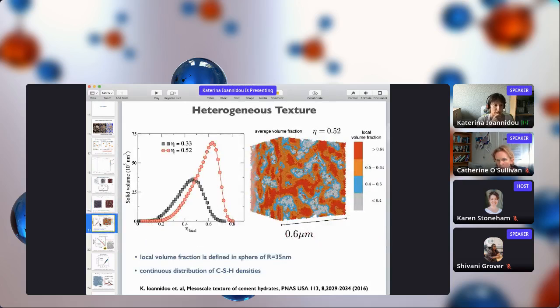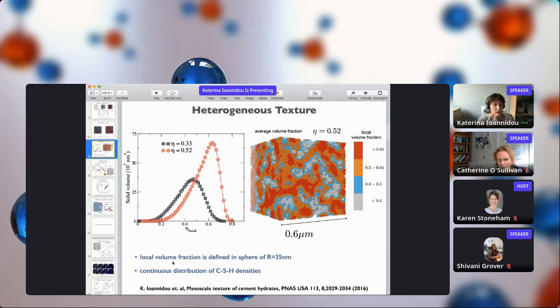Of course, all these things have a meaning only if we can validate the results we get and they are meaningful for cement. So a way to characterize the structures is by getting the distribution of local volume fractions. Here you can see the local volume fraction, which the higher one is in red, larger than the close packing fraction, forming this red network that is percolating inside the solid and is also bearing the load. We see that inside this material we have a continuous distribution of different volume fractions. So it's far, far away from being a homogeneous material; it's mainly driven by heterogeneities.